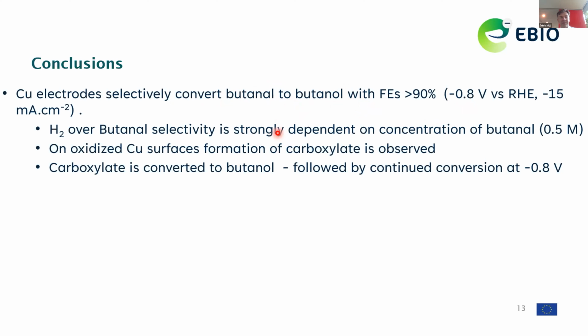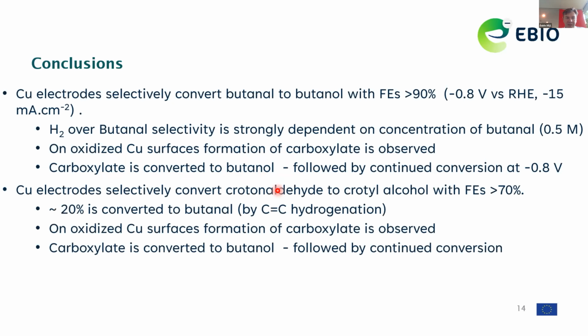I said that already, so that leads to the application of flow reactors rather than batch reactors to maintain a relatively high feed concentration. On oxidized copper surfaces, carboxylates are formed, and once the copper surface is fully reduced by the electrochemical potential, also the carboxylate disappears, and conversion of the aldehyde and perhaps some of this carboxylate to the alcohol is feasible.